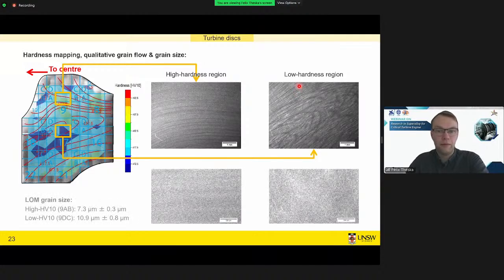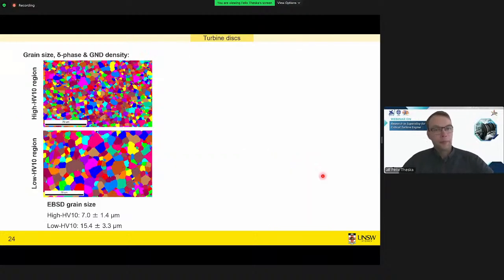Now, if we take these samples into the light optical microscope, we see that the low hardness region also has this larger grain size. Here are some areas with larger grains. If we take it again into the electron microscope and do some EBSD, we can confirm that finding where we have a larger grain size. However, this grain size difference is not enough to account for the observed differences in the strengths. So there must be more going on.